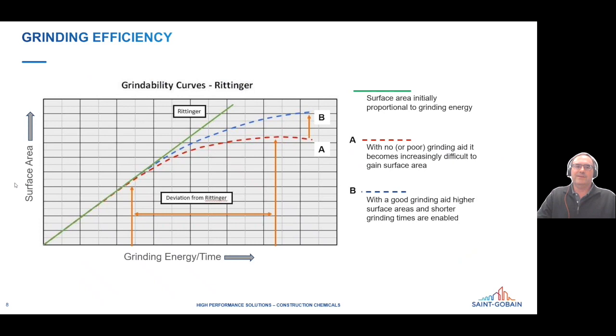So the red dashed curve indicates what happens without a grinding aid. You actually get less and less efficient, and you can reach a point where you stop increasing the surface area, right? You can't increase it forever. When you use a grinding aid, because it improves that efficiency, you get less deviation from linearity. You can grind to a finer maximum fineness, and if you have a set fineness out in this range here, then it takes you less time to get there, and that's a big advantage when you're talking about an industrial process. If you could do the same thing in less time, that's always better.